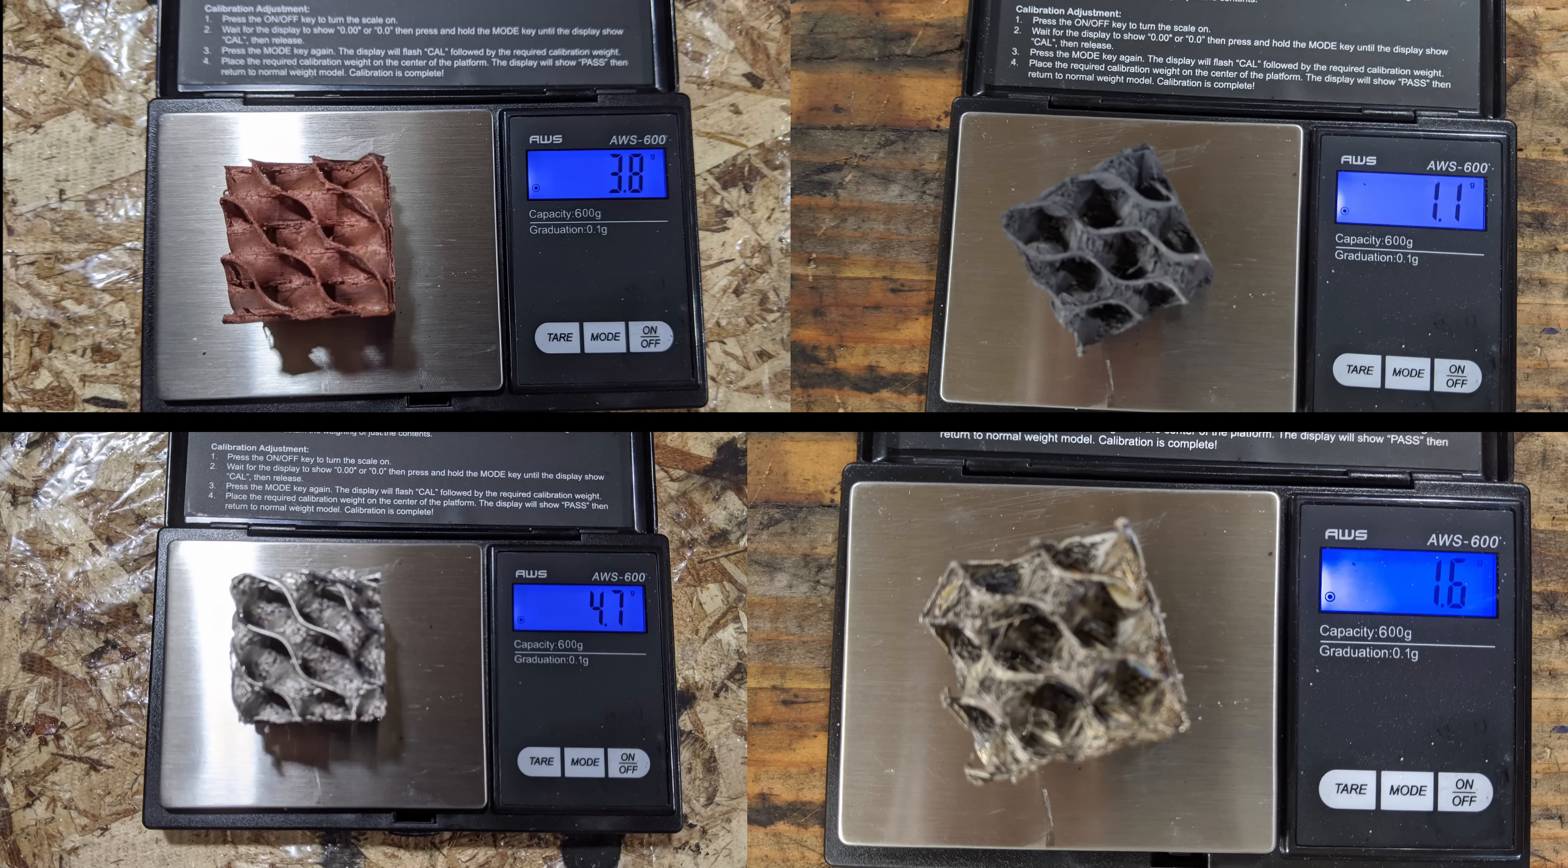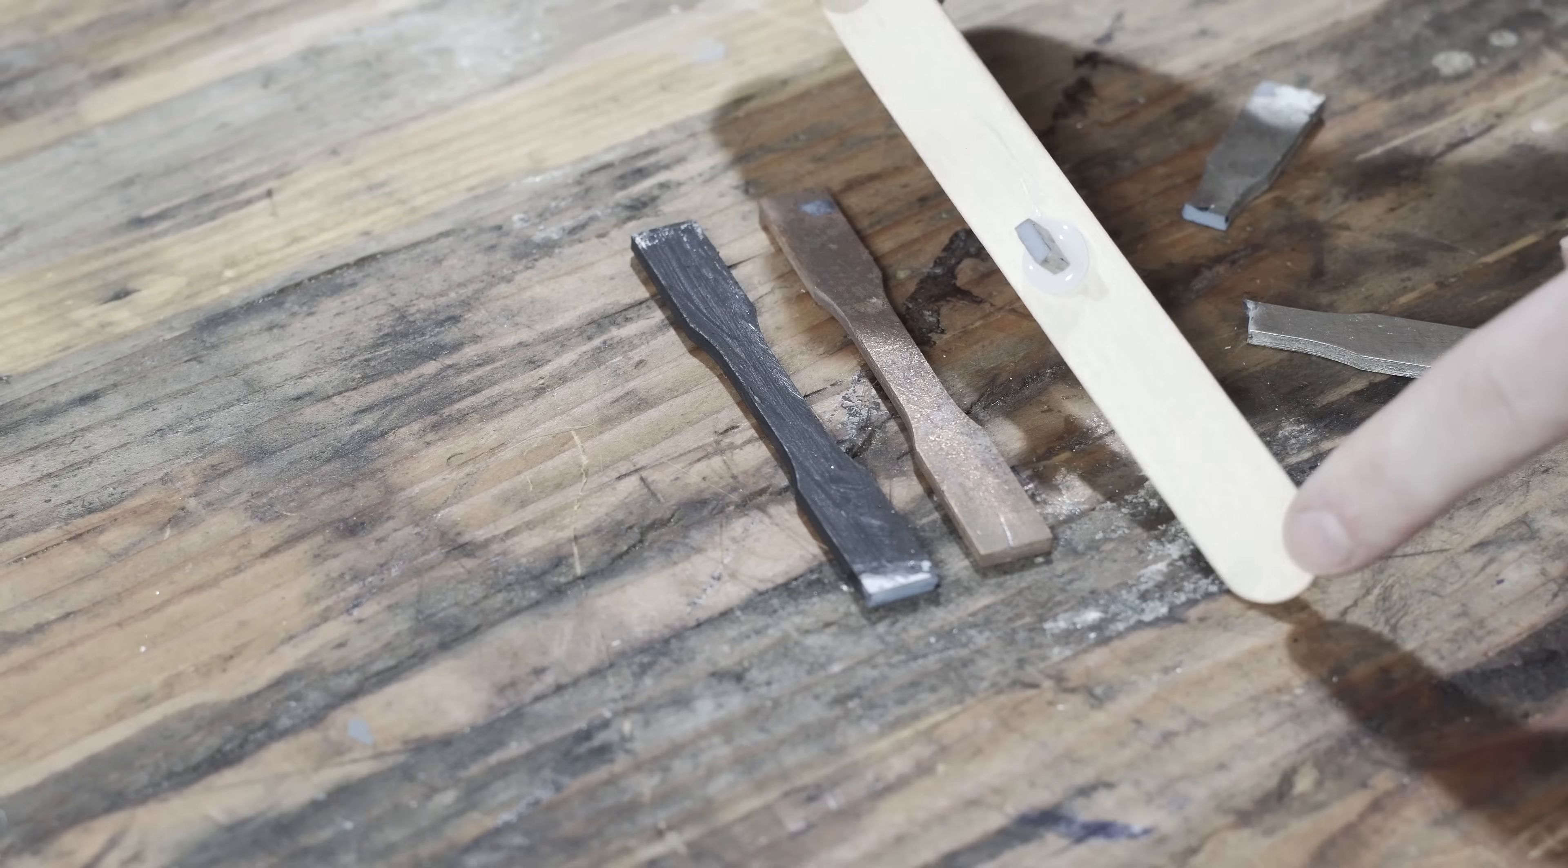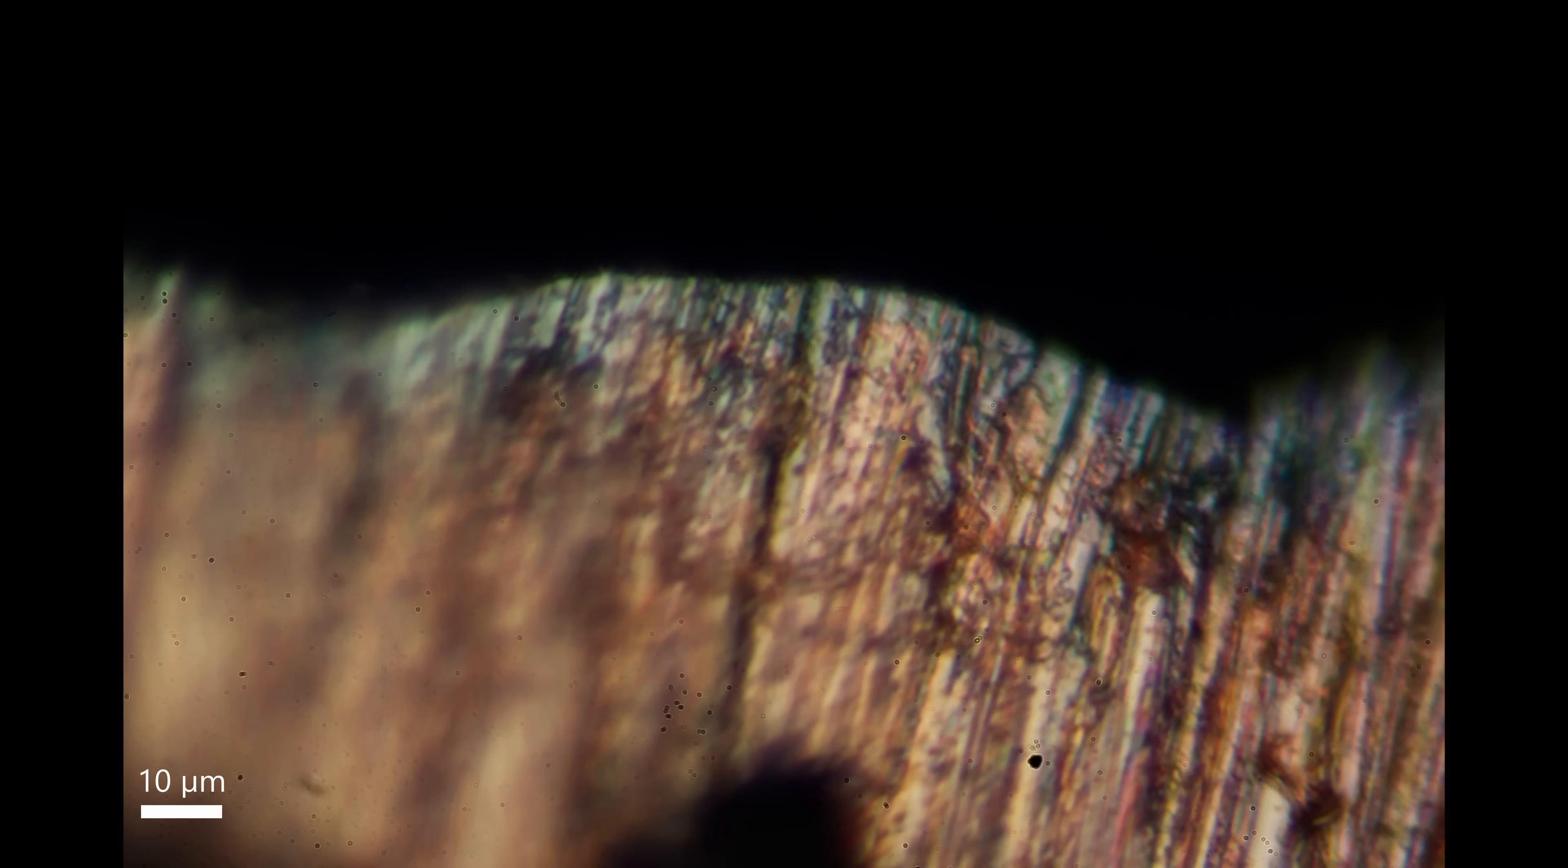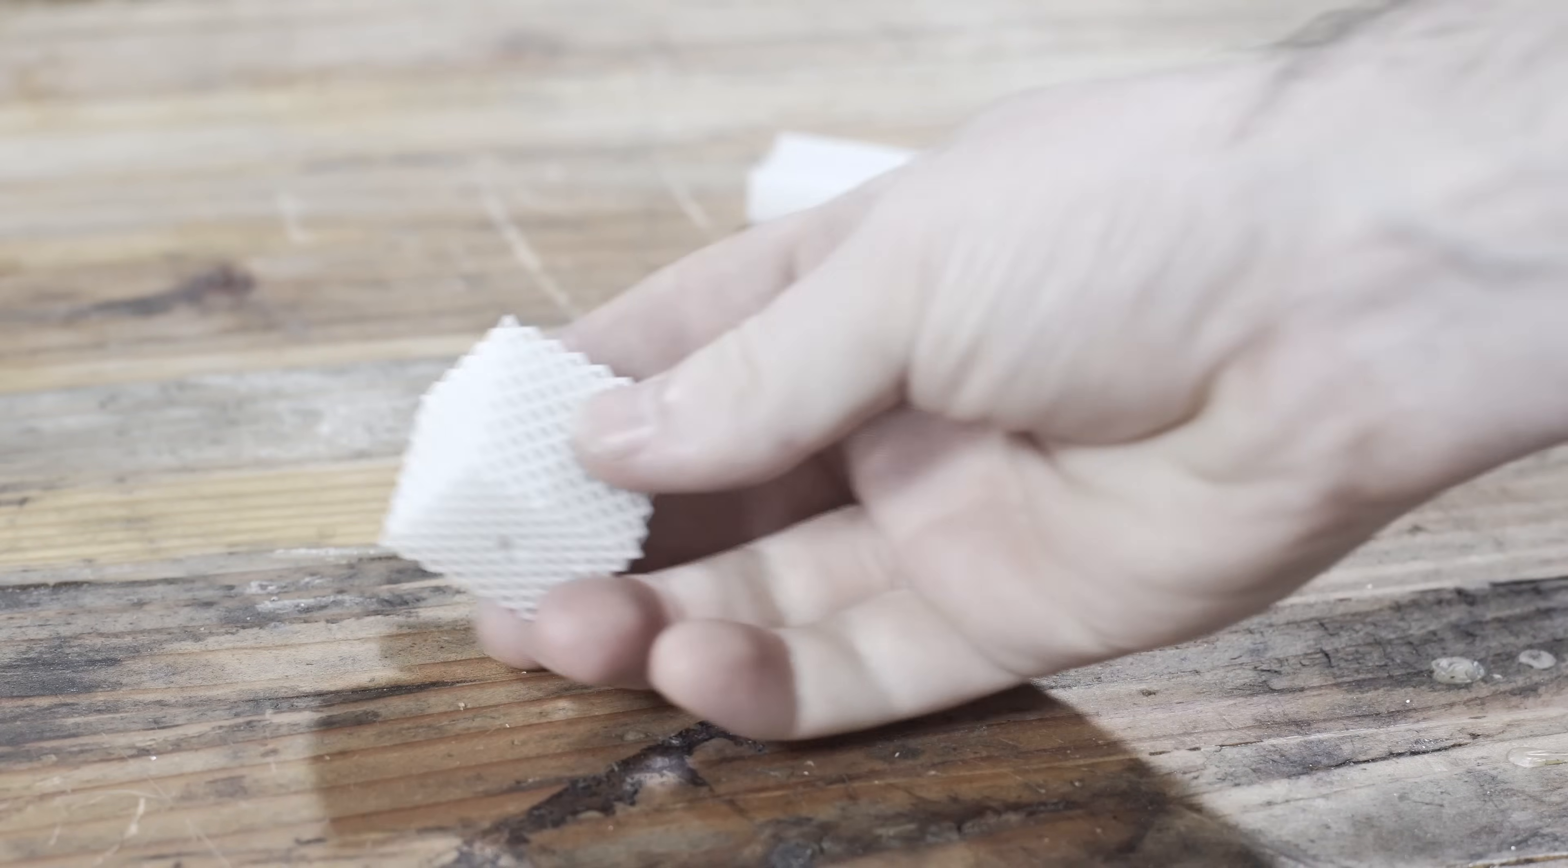Both samples saw a mass reduction of about 65 to 70 percent, and when you section a small piece of these and look at how thick the plating is, it looks like it's about 60 microns on average, depending on where you look. 40 to 50 microns of that is probably the copper, and about 10 microns is the nickel, although it's hard to tell because I didn't have anything to preferentially etch or color one metal versus the other. So it's a little tricky to see in the microscope. All in all, I'm pretty jazzed by these results.